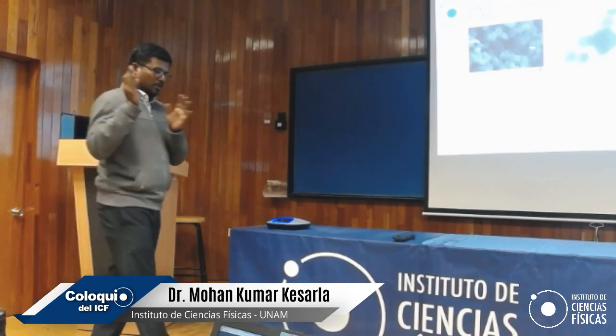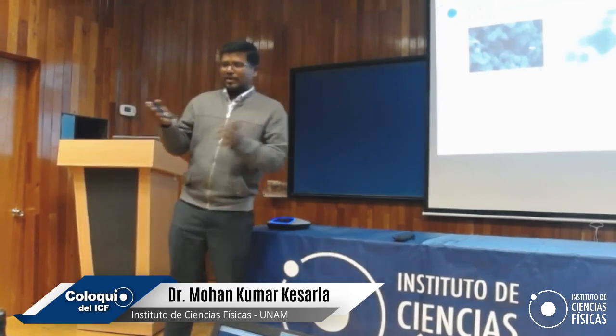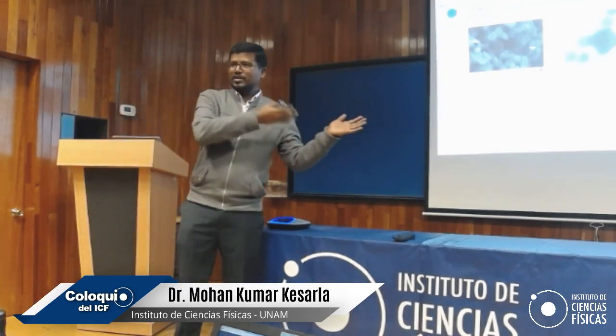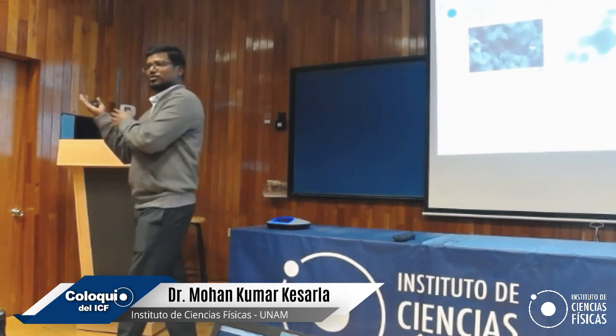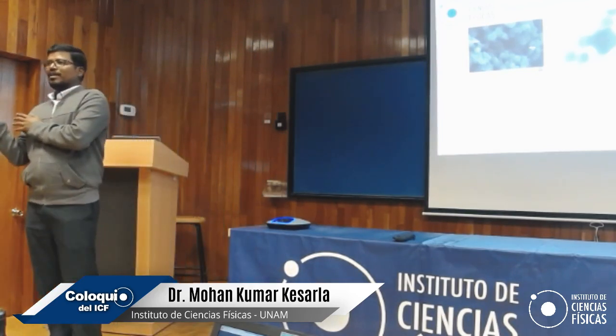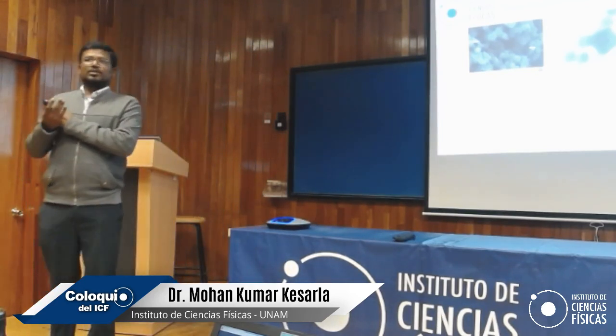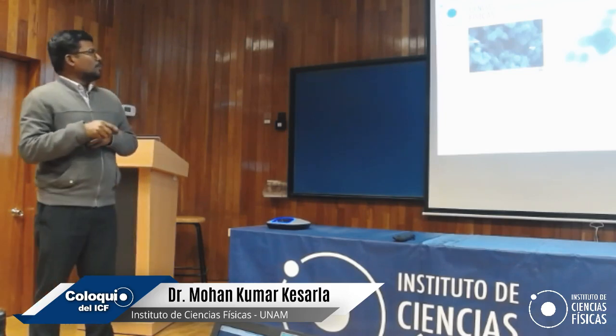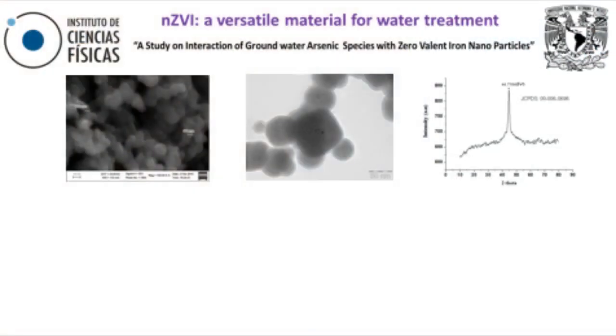So don't think that all the zero valent iron we can convert with any of the polyphenols. We can't convert any iron 2 plus to zero valent iron. It is not possible. We want to check the reduction potentials of both. So we managed to make the stable iron, and if you look at this in a high resolution transmission electron microscope, there is a core of zero valent iron, and there is an outer shell, which is iron hydroxide, iron oxyhydroxide.